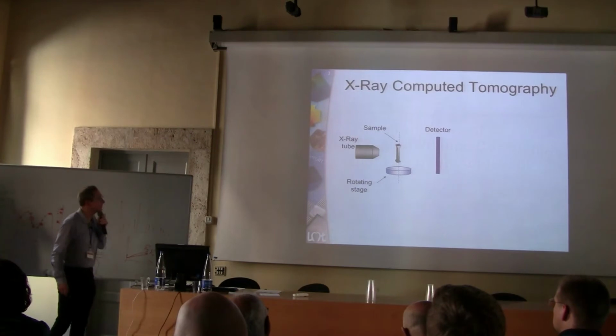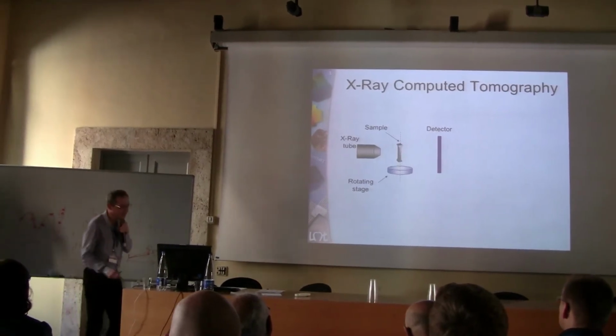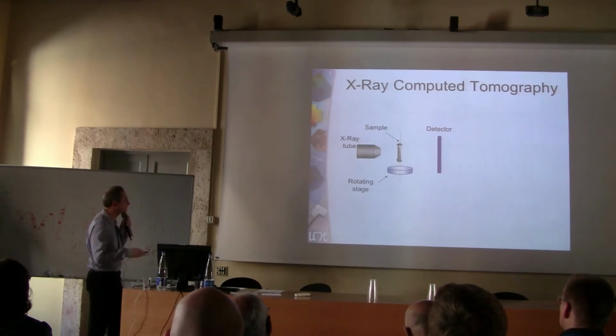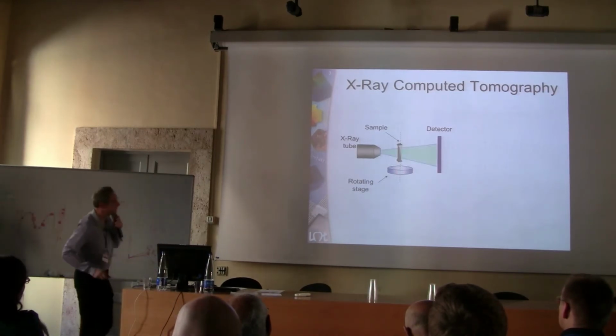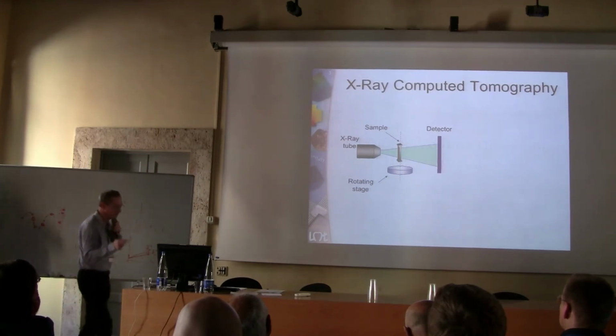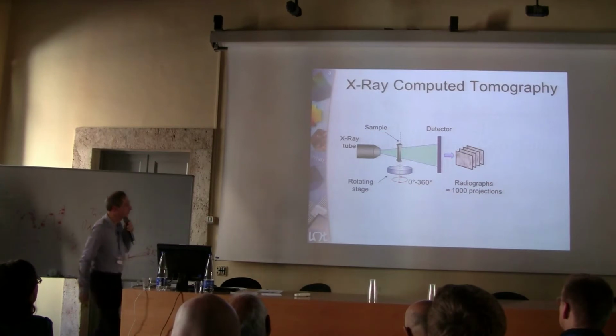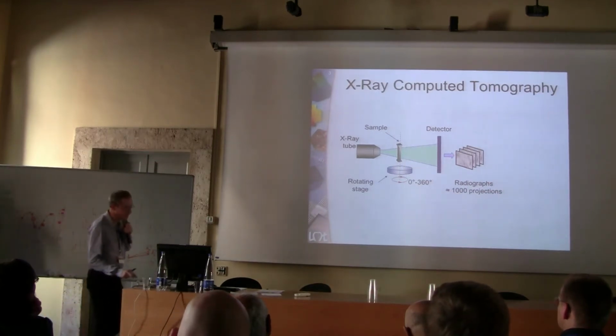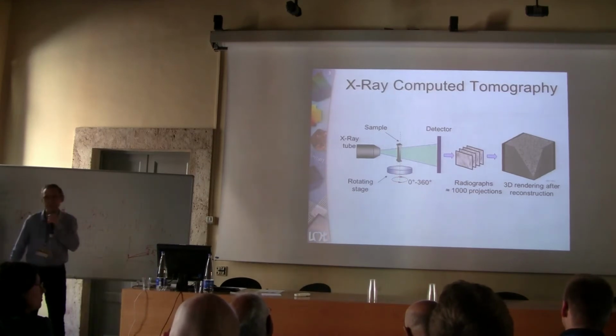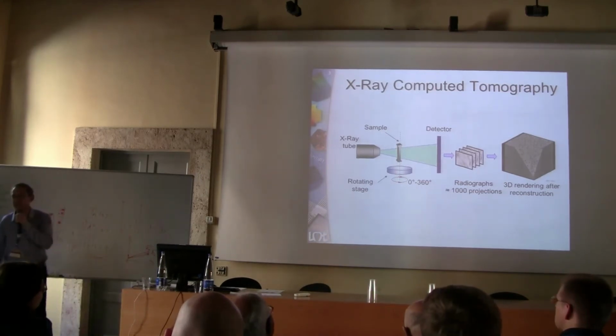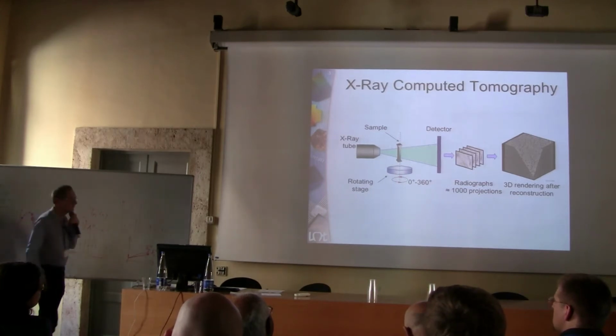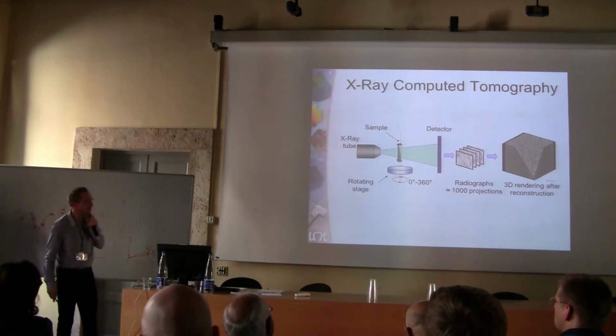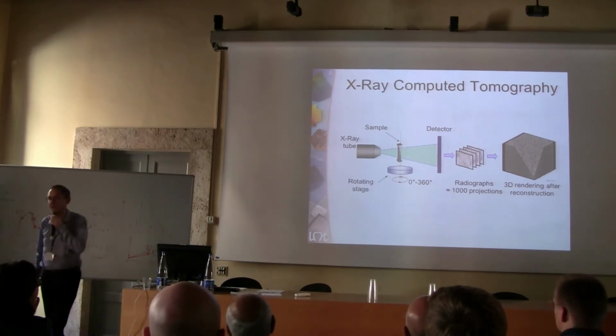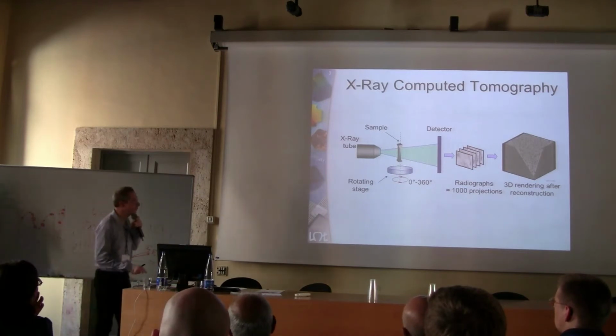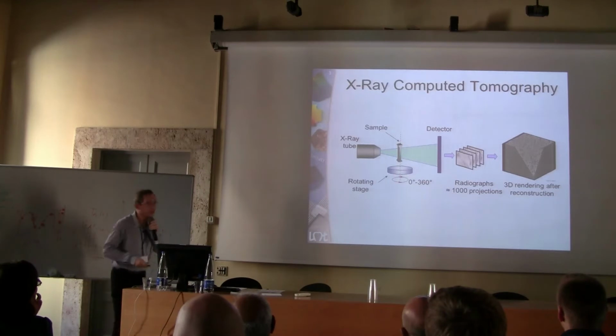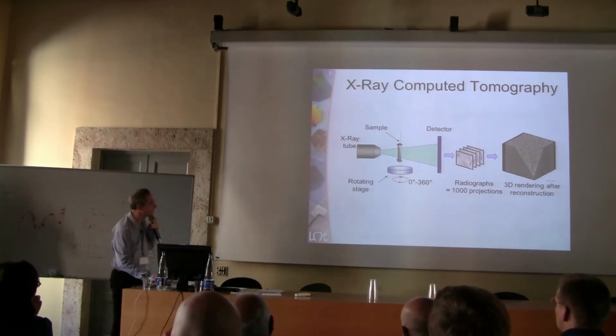One way of getting 3D images is via X-ray computed tomography. You have an X-ray source, you illuminate a sample, you have a detector, and you gradually rotate it, acquiring a series of radiographs, with which you reconstruct 3D volumes. This imaging technique is interesting for people like myself, whose background is on the mechanics of materials side, because you can image a sample without destroying it, even as you load it.